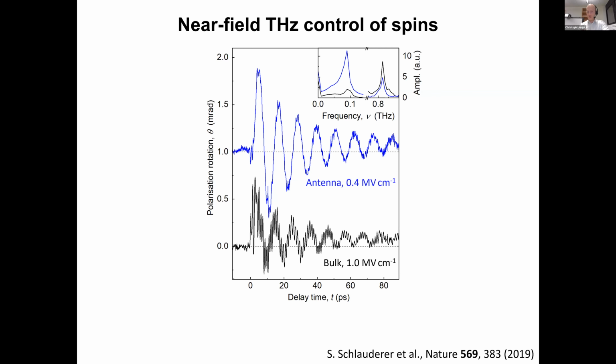We have achieved the strong scaling with the antenna, and at the same time, as a byproduct, the Zeeman-launched mode has completely disappeared almost. That's for two reasons. First of all, with higher field amplitudes, of course, the electric field dipolar transition mode will dominate, but at the same time, the metamaterial, our resonator, only selectively enhances the electric field and actually even suppresses the B field. So that's two ways by which we now have a preference for the desired magnetic mode.